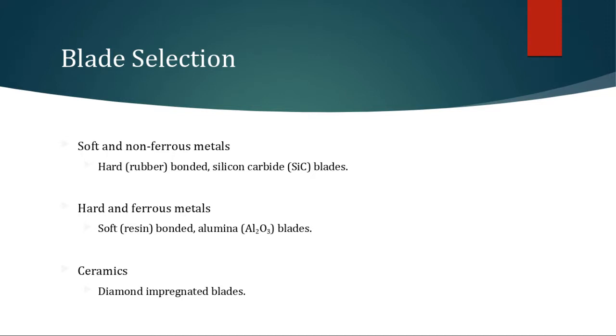Okay. Because some of these soft materials, one of the things it does is they can smear onto the blade itself. So the purpose of this, because of the fact that these are small, soft materials, as you're cutting with this rubber bonded blade and it's holding the silicon carbides in place, you have a fresh cutting surface all the time. The hard ferrous metals, the soft bonded blade, if you were to use a rubber bonded blade on a tool steel, something that has a very high hardness, then what you're going to end up doing is, the particles themselves on the blade aren't going to hold long enough.